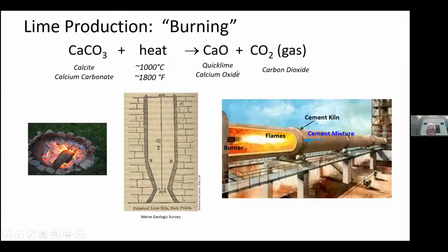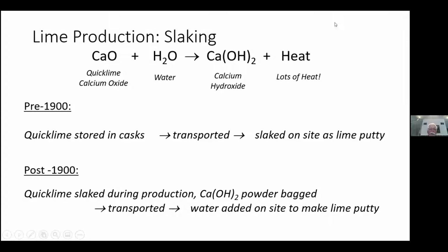Now, once you've burned the lime, the next step in making use of it is to slake the lime. Slaking means you put it in the presence of water, and it starts to absorb some of the water, chemically react with it, and produces calcium hydroxide. Now, that process, as I mentioned in that earlier lime cycle, is a strongly exothermic reaction. And so a big part of the heat that you put into burning the lime is re-released as heat during the slaking process.